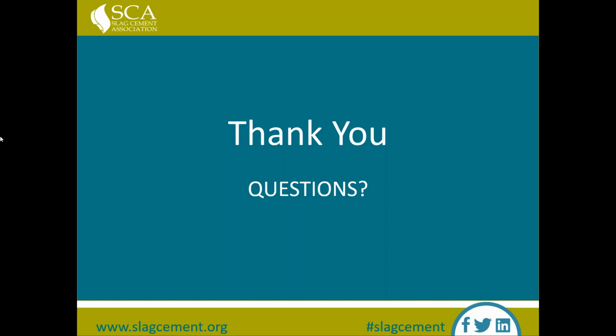And so there is a lot of data out there that shows, I think ACI 233R covers that as well. But I know that specifically this question has come about in places like Florida, and some other coastal places where we're importing slag granules or finished slag product. And that slag can be from places like Southeast Asia. And in Southeast Asia, the slag products, the slag granules, the slag cements that are produced from those plants tend to have high alumina. In more domestic sources, it tends to be fairly low, but there are other places where you see these varying amounts.